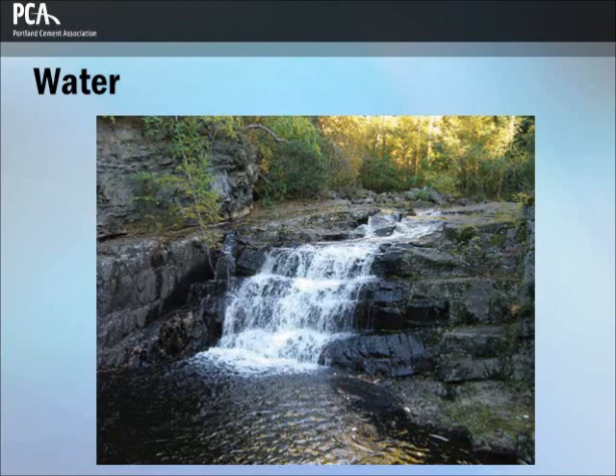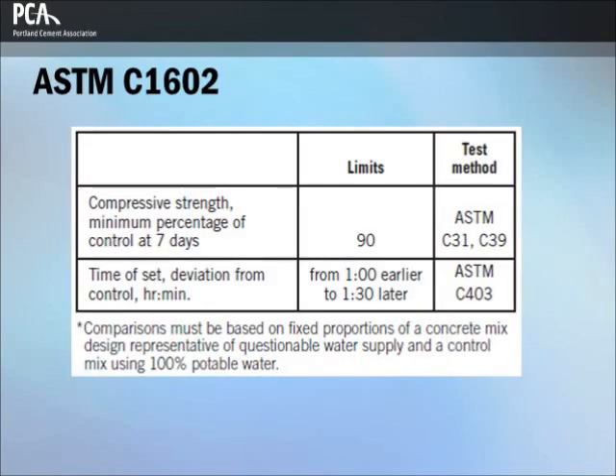Almost any water that is drinkable and has no pronounced taste or odor — also known as potable water — can be used as mixing water in concrete. Many waters that are not fit for drinking are also suitable for use in concrete. Acceptance criteria for water to be used in concrete are given in ASTM C1602. Potable water can be used in concrete without any testing or qualification.